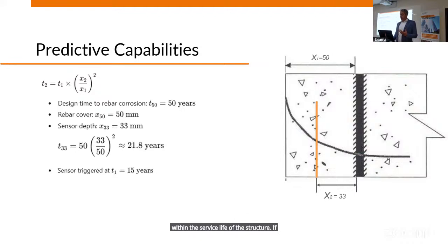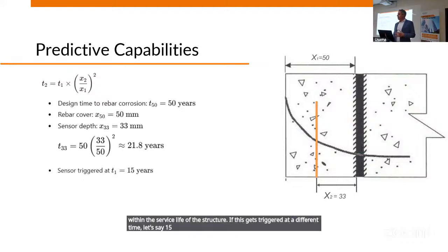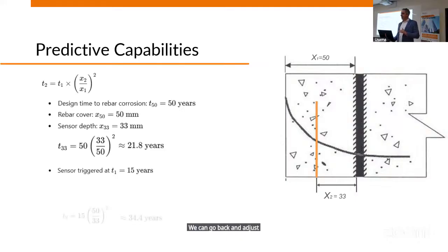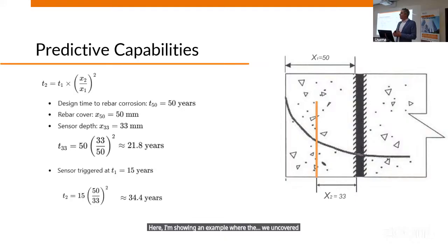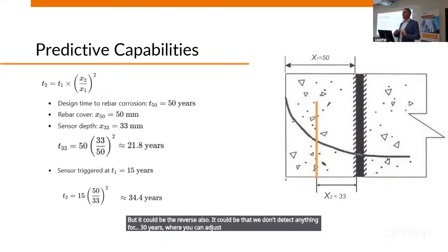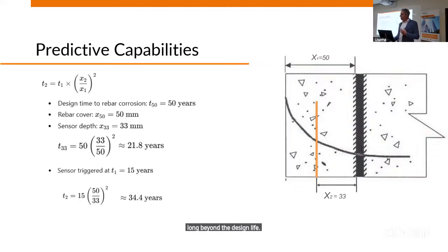If this gets triggered at a different time, let's say 15 years, we can go back and adjust the service life based on actual data that we're getting in the field. According to this calculation, this has a 34-year service life. Here I'm showing an example where we uncovered things earlier than they're supposed to happen, but it could be the reverse also. It could be that we don't detect anything for 30 years, where you can adjust and give the assurance to the asset owner that the structure will last long beyond the design life. So it gives us a field method of validating the design life, validating the service life based on actual data.